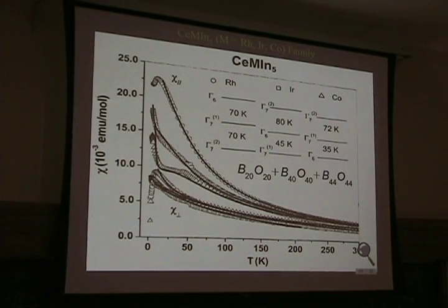Okay, so in principle, as experimentalists, I have the data, I can try to fit with the simple idea. So that's a tetragonal crystal field Hamiltonian. And actually, you can fit and reproduce the main feature of the data just by this Hamiltonian. But that's really dangerous, right? That's really dangerous to do, because this Hamiltonian is not as simple as it looks. So you can change these parameters randomly, you can reproduce the data, but there is no physical meaning. So you should be very careful.